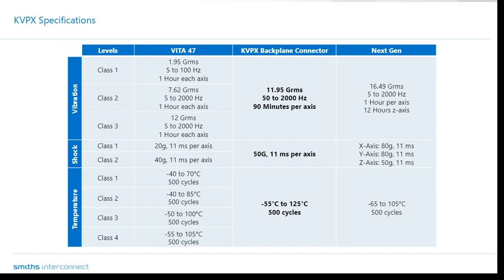For shock, as you can see, our current specification exceeds the current VITA-47 maximum requirements, which is class 2 in this case. The 50 Gs instead of 40 Gs at 11 ms with the sinusoidal response spectrum. However, again, we've done some recent testing to show up to 100 Gs at 6 ms with a sawtooth response curve, which postures us for next generational system requirements. For temperature, finally, the KVPX connector system is well suited to meet all ranges of the current system level temperature requirements, while current qualification testing is not far from next-gen systems.